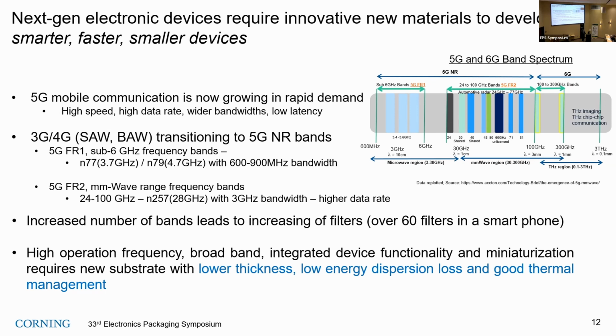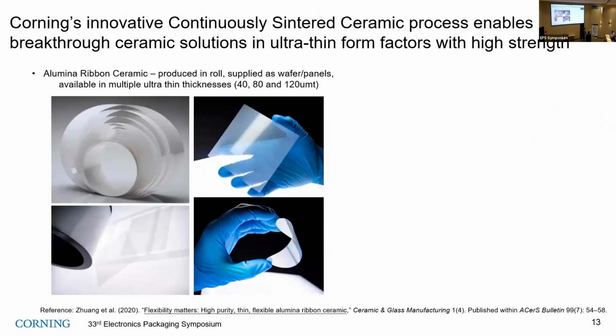High frequency operation, broadband, and integrated device functionality with the number of filters mean miniaturization is needed, which requires a new substrate with lower thickness, low dielectric dispersion loss, and good thermal management. So for this, Corning innovated a continuous sintered ceramic process, which is basically sintered alumina. It has a very ultra thin form factor. Right now it is available in roll-to-roll format, and from there we can dice it into wafer format or different shapes.